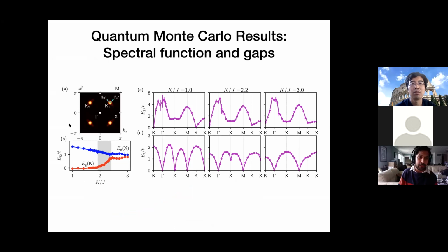And then you can also look at A(k, omega). You can clearly see nodes in some regime, in the regime where the D wave order parameter survives. I'm just showing the spectral function, and these are the various cuts as a function of K over J. So when K over J is small, that is J is large, you have nodal D wave. These are the nodes at the K points. And when K over J is large, you don't have any nodes. In the intermediate phase also, you don't have any nodes, as I already argued based on the mean field argument, and all that is correct. Everything seems to match.